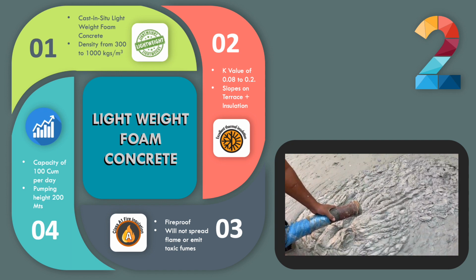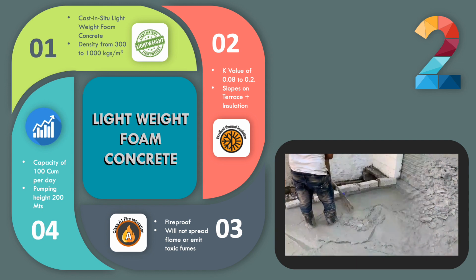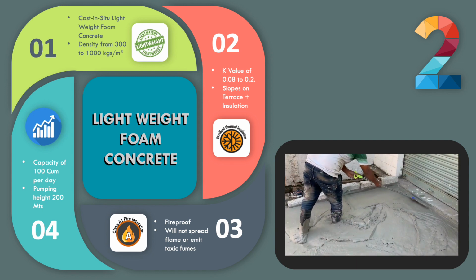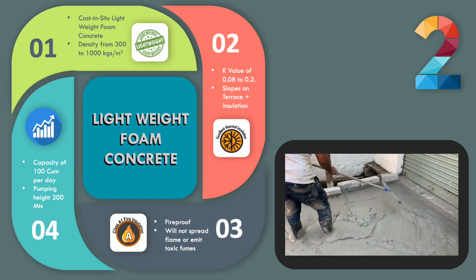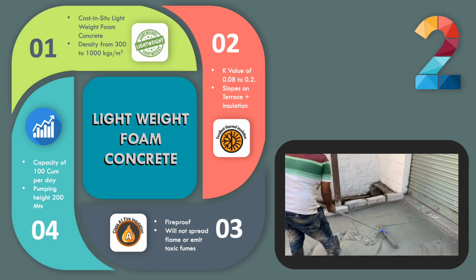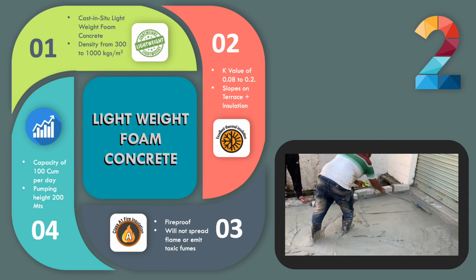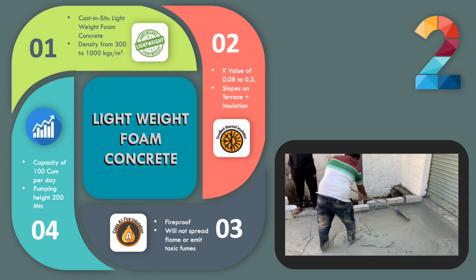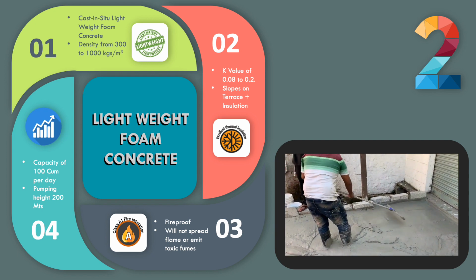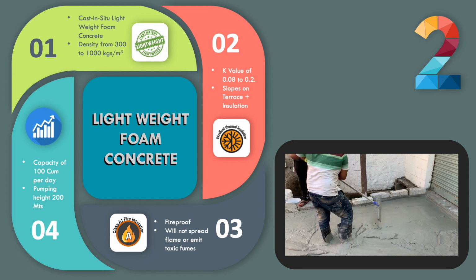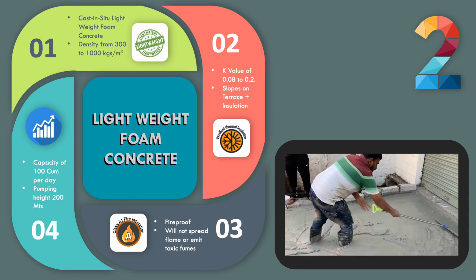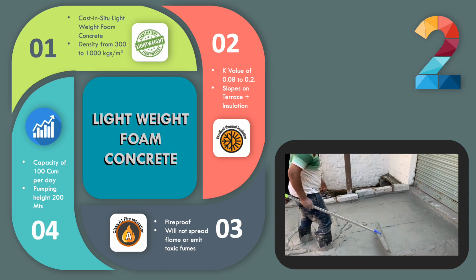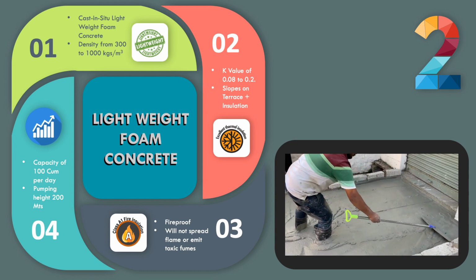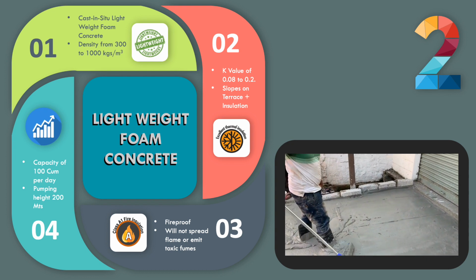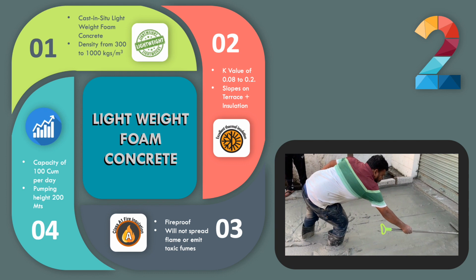The produced foam concrete is filled in a large collection tank from which it is pumped up by the heavy-duty slurry pump through a high-pressure flexible hose pipe. The foam concrete is filled in layers of 5 to 6 inches at a time and leveled using a rubber squeegee. For larger sunken slabs, it is preferable to allow the first layer to dry and settle prior to the next fill. GEC can complete filling of large areas in short time using this technology. Please feel free to call us or email us with your requirements of foam concrete.